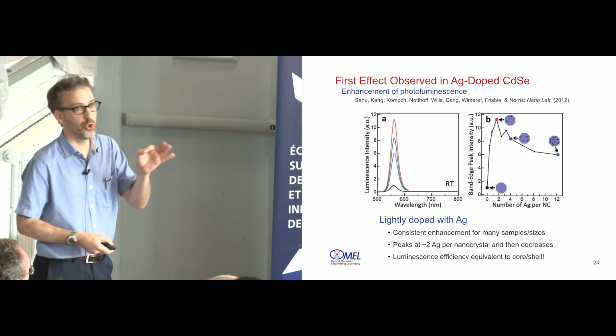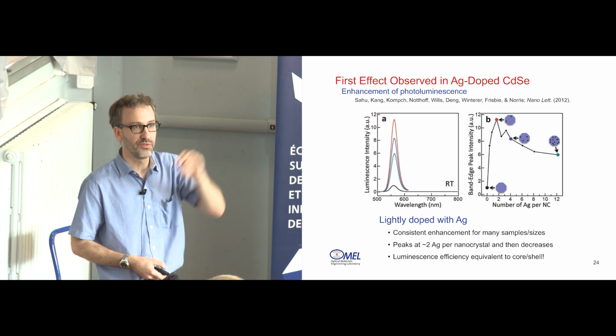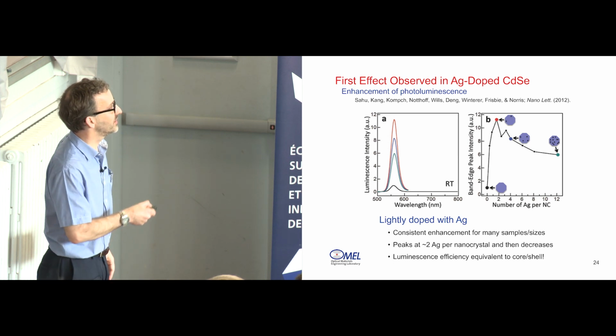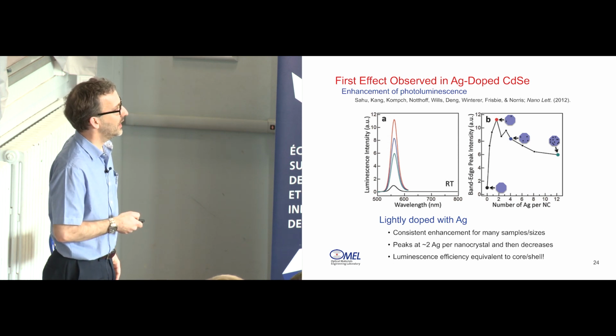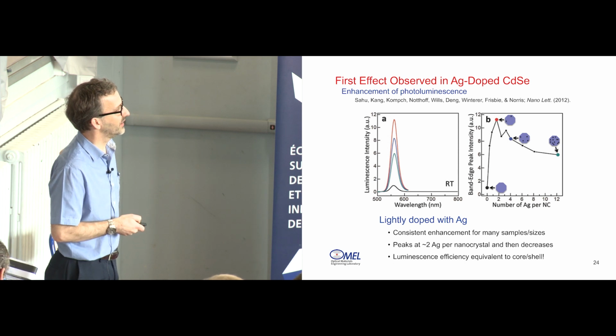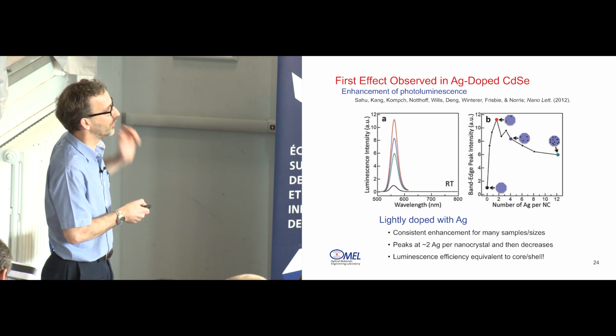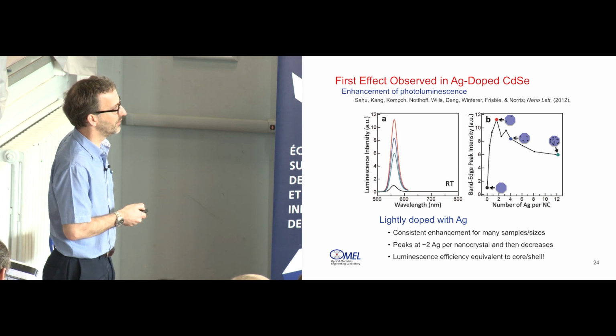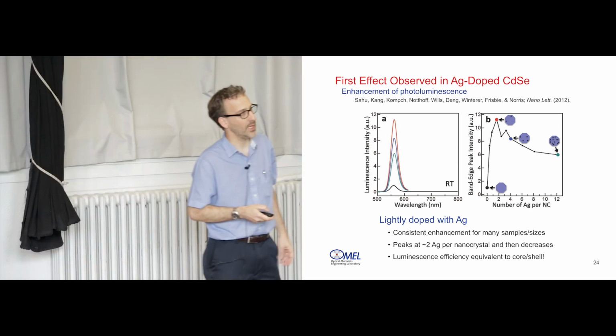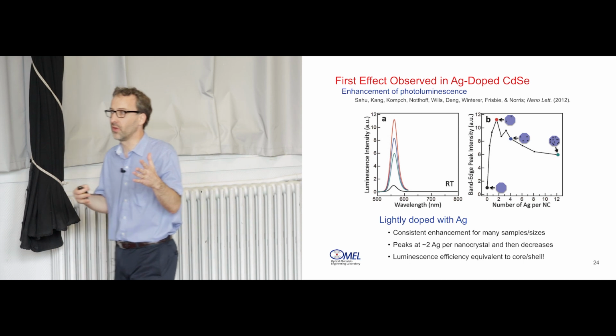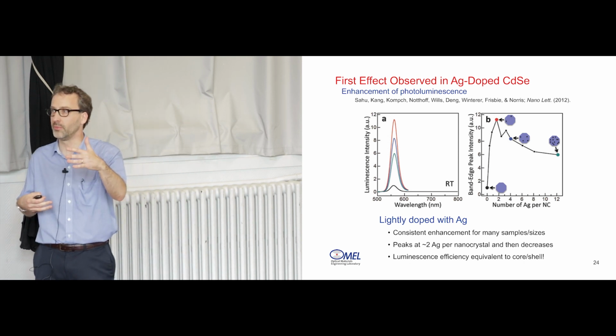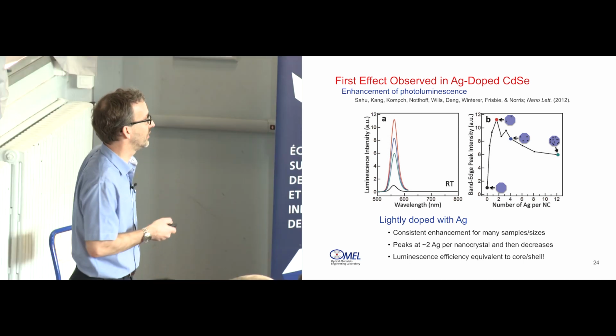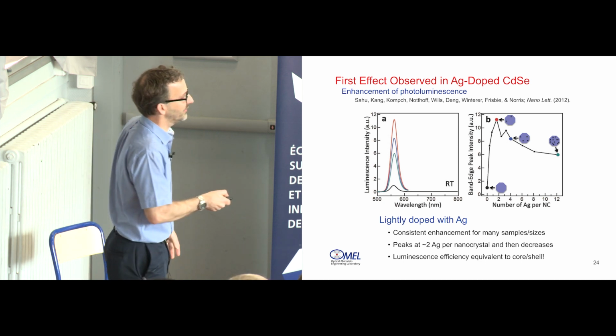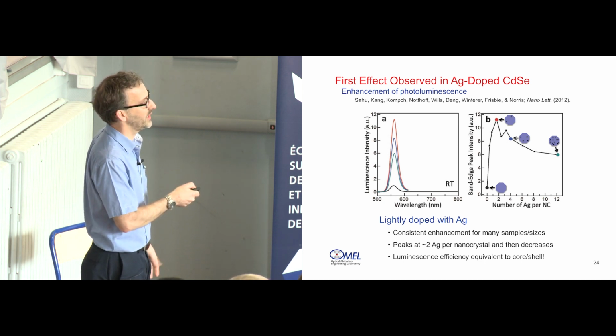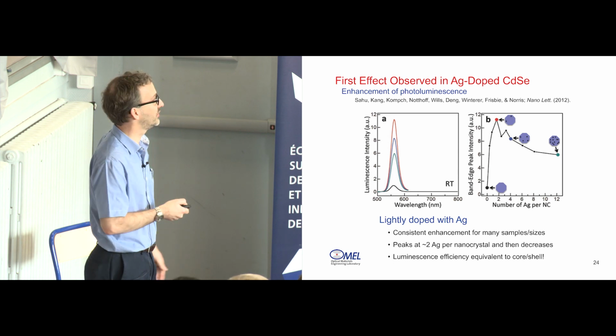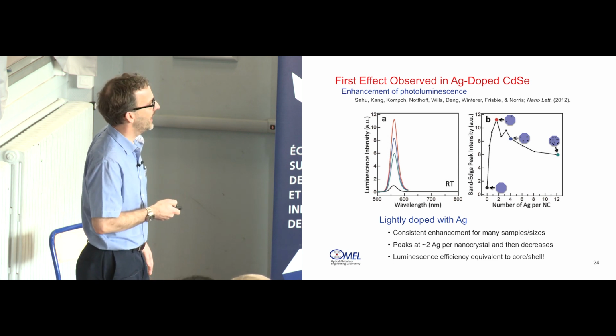And when he just added 2 silver on average, just a whiff of silver to the nanocrystals, the fluorescence intensity went up by a factor of 10. So going from 0 to 2 on average. And then as he kept going, it came down when he went to 4 and 12, but always above where it started. And I didn't believe this at first because, as we've already heard, if you put in an extra carrier, you have the possibility to quench the photoluminescence due to Auger. So he did it on many different samples, many different sizes. It always peaked at about 2 silver impurities.